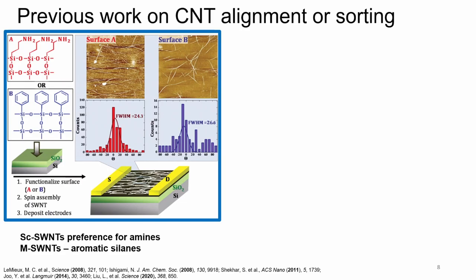And it's been shown that through this functionalization, we can have a preference for either metallic or semiconducting tubes. However, the alignment wasn't uniform throughout the surface in this work because the solution of the tubes was drop casted on a wafer and then spin coated. So it went really, really fast at a high RPM, and it wasn't even throughout the surface. But there was some selectivity there.